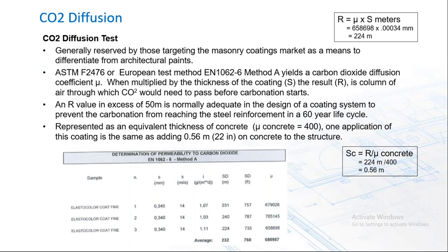You'll see coatings manufacturers will trot out a CO2 diffusion test. There's a lot of science behind this, but really at the end of the day, we're talking about creating an effective carbonation barrier to prevent that wave front from even entering the concrete. And where you'll see a tech data sheet from a manufacturer with an R value, not to be confused with insulation, but an R value in excess of 50 meters, this means that it will prevent that carbonation wave front from reaching reinforcing steel in 60 years. So we're talking a very effective carbonation barrier.